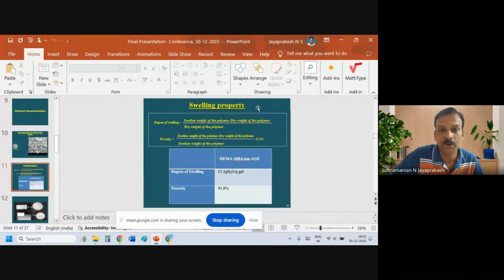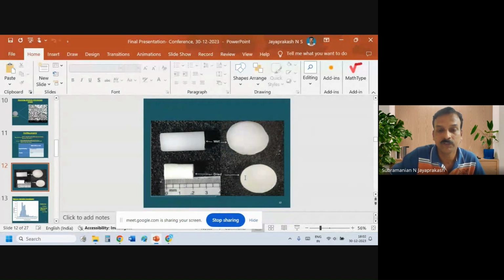And we did the swelling property and we got the porosity up to 93.8%. And if you can see here, the degree of swelling is 15.3 grams of water per gram of gel. So here in this picture, you can see both the wet gel as well as the dried cryogel material.